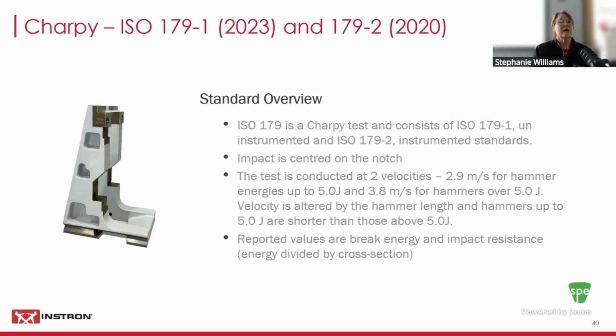ISO 179, similar to D6110, and that it's Charpy. However, ISO has two methods. They have -1, which is uninstrumented, and then -2, which is dedicated to a fully instrumented test, meaning we have software, we have data acquisition, we have an instrumented load cell or hammer that are impacting the sample. Same as D6110, the sample is in a horizontal position, notch facing away. We center on the notch.